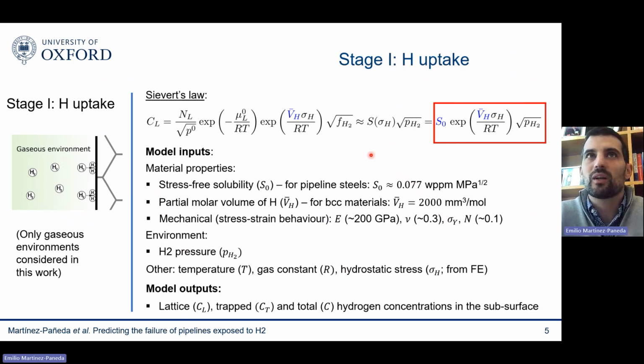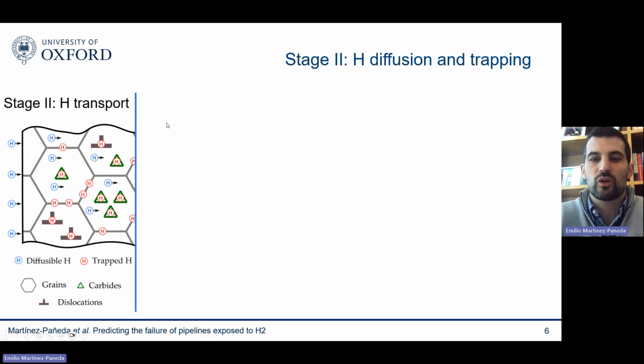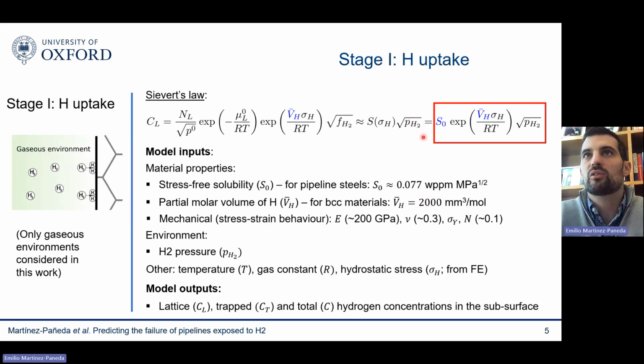So what do we need here, basically? What are the inputs of the model? So the model is able to predict the lattice hydrogen concentration as a function of the pressure of my gaseous environment. And then the only properties that come into play is the stress-free solubility. This is something that we know. It has been measured in the literature multiple times. The partial molar volume of hydrogen in the solid solution. So for BCC materials, we know again what's the number in there.